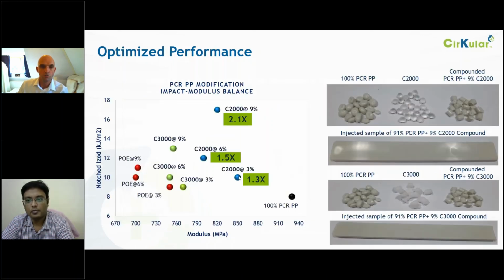Well, this is an overview of how our compatibilizers work, and this is actually an example of a soft phase being dispersed in a hard phase matrix, but there's also the compatibilization effect. I think Professor Venneman showed a nice image of small rubber bits in a hard matrix. That's more or less what you have at 9% addition. You start having those domains, but if you go to a much lower percentage addition, you do have the compatibilization effect. So you do already increase your impact strength quite a bit, but you don't have this significant loss in modulus that you often see when you add more.